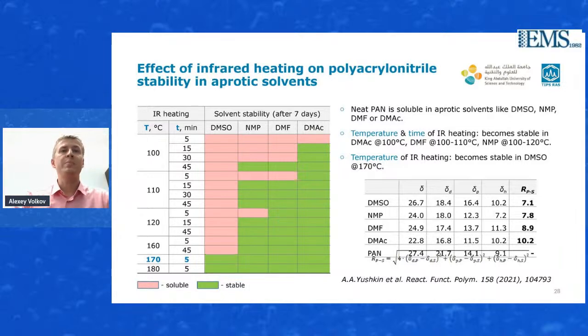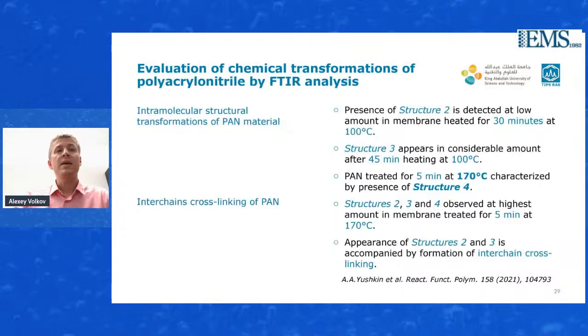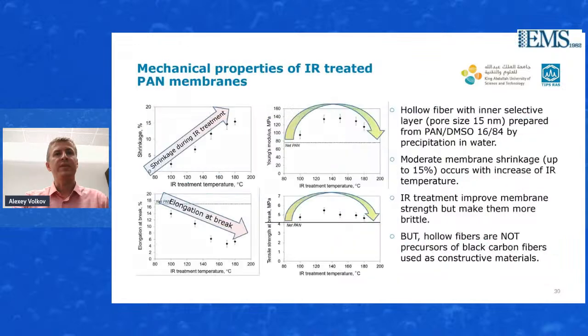That's DMSO, NMP, DMF, and dimethyl acetamide. And that's quite interesting. I will skip that because there is a problem with the visualization. But what I'd like to say here is, in terms of molecular transformation of the PAN material, the forming of the double bonds and the cycles transforms that material into a non-soluble form, which can be used later on for organic filtrations.